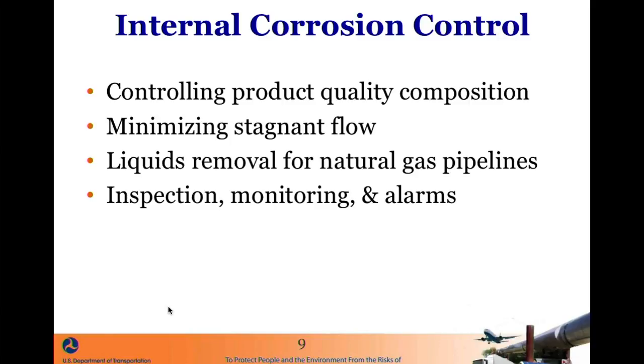So the main way that we control internal corrosion is by making sure that the product inside the pipe is not corrosive, and we do that by controlling the impurities in the pipe. There's a lot of monitoring which takes place, and for natural gas, the FERC tariff requires 7 pounds of water maximum per million cubic feet of natural gas, and a lot of times, the customer has specifications for the amount of quality and impurities that are allowed in the product.